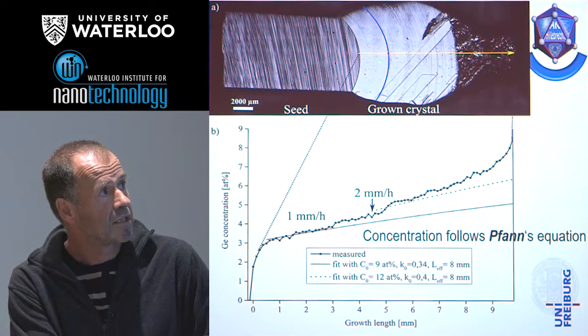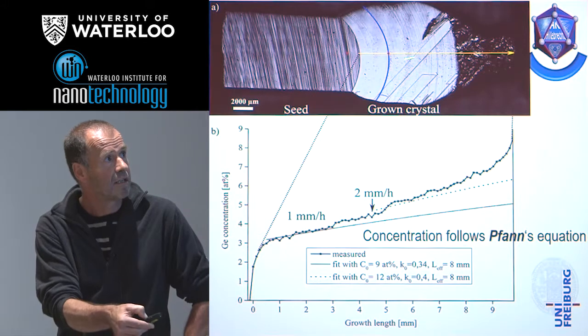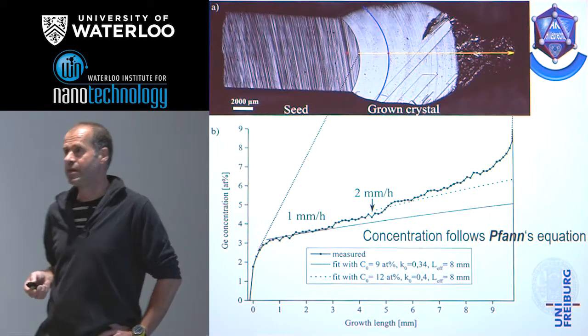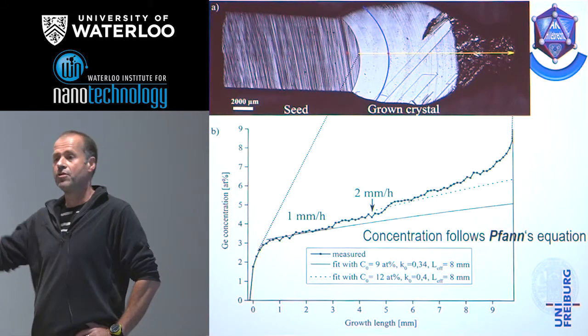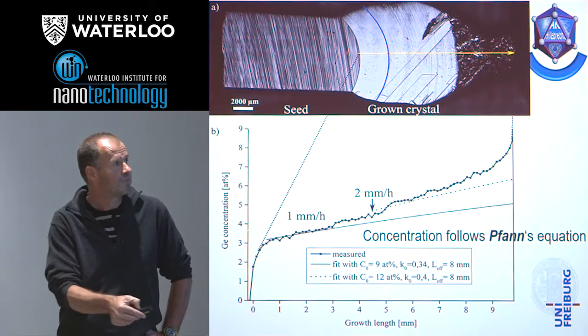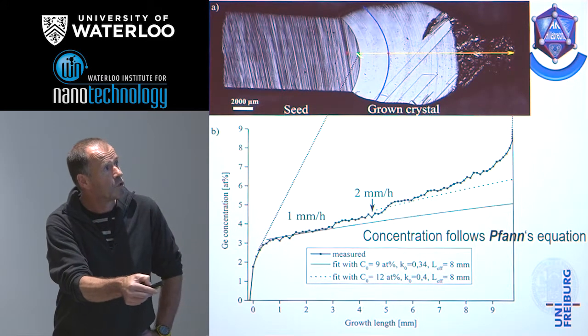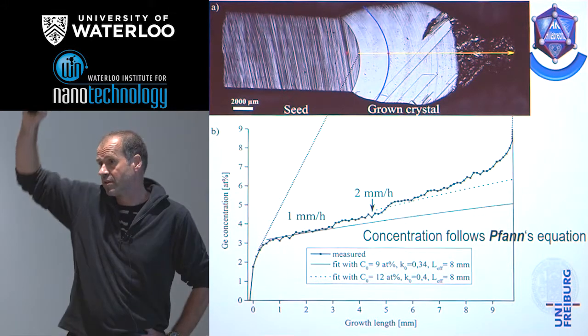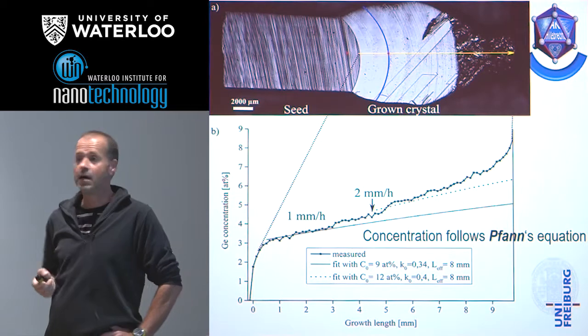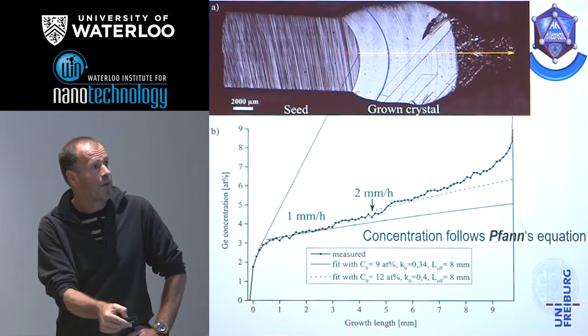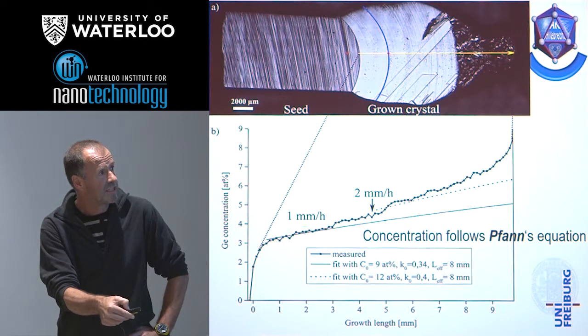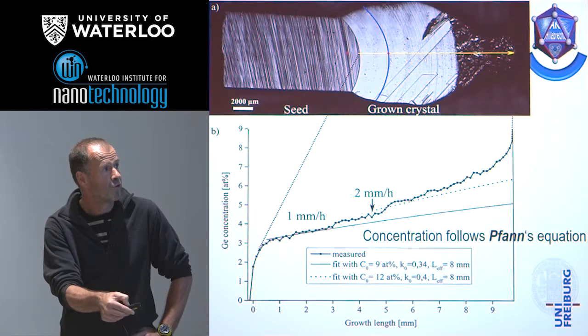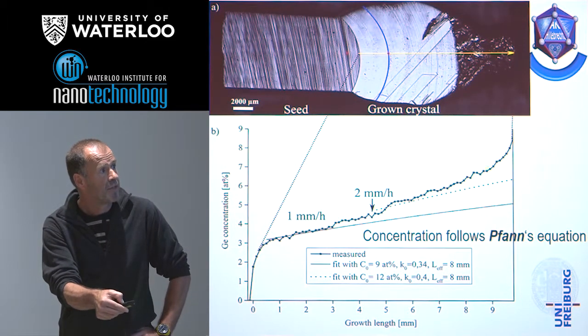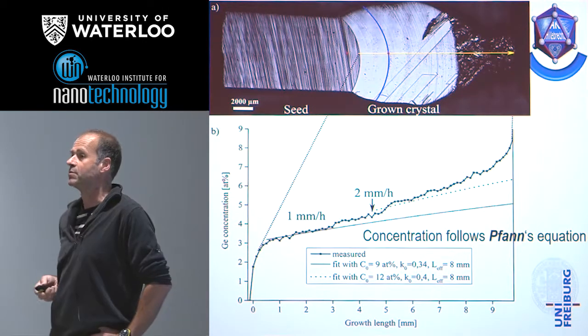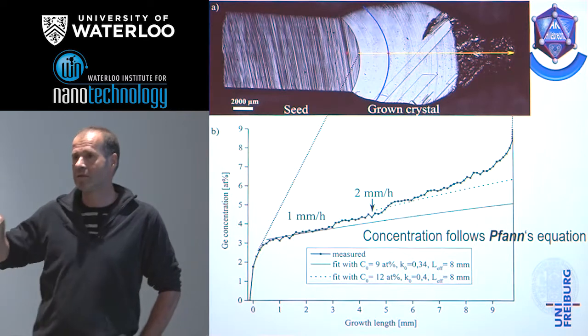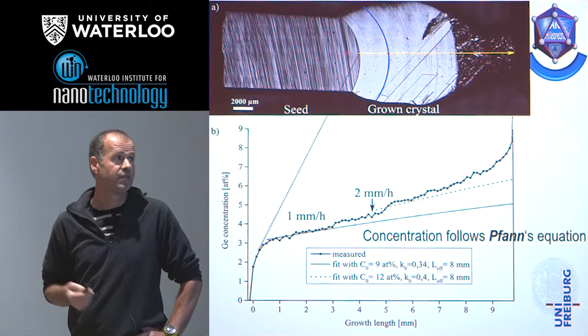We had a starting material and we could show that there grows in fact a single crystal, and according to the separation and the different solubility of germanium in the solid and in the liquid state, we get a difference of the concentration according to the size or the distance to the starting material. That's a situation which is quite well described by the equation of Pfann, and you could see even the influence of a shift or change of the growing conditions is visible in the change of the germanium content.